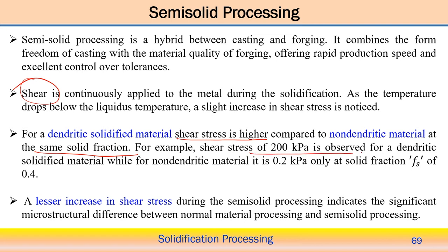You can take an example also. For example, a shear stress of 200 kilopascal is observed with a dendritic solidified metal. The metal having the dendritic structure might have a shear stress of around 200 kilopascal. But with the same solid fraction, say a solid fraction equal to 0.4, it creates only 0.2 kilopascal shear stress for the non-dendritic material. Therefore, it has some influence on whether a non-dendritic structure or a dendritic structure is formed.